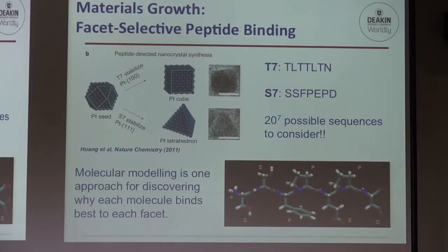It's also been shown quite recently that you can use these peptides to do another one of the jobs that I mentioned earlier, and that is to control the shape of a nanoparticle. So in this case, it's a beautiful example where they're able to use peptides to control the growth of platinum nanocrystals, where if they can stabilize the 100 surface, they're making cubes, and if they stabilize the 111 surface, which are these triangles here, they can make tetrahedra.